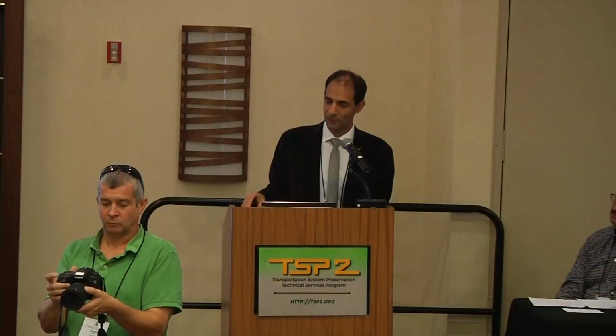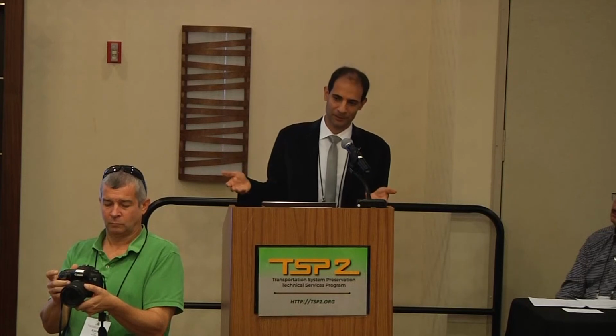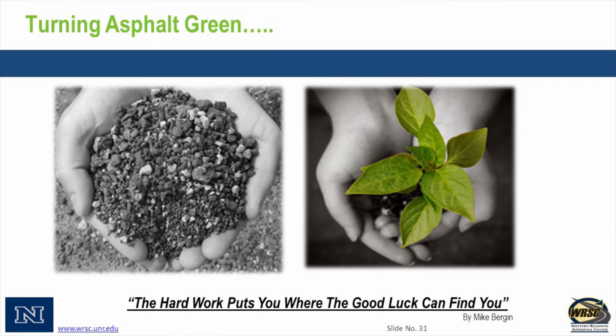Going back to your earlier talk, what was the optimum time for the second slurry seal? In terms of years, it's basically 4 to 6 years from the first one. In terms of PCI, which I like more, because most likely you can take this and implement it in your agency better, since the climate is different and the material is different. It might take you maybe 5 years for the first slurry seal to reach 90, whereas in Washoe County it may only take 3 years because the environment is different. Or if I take that data down to Vegas, which is a totally different harsh environment, maybe in 2 years I will reach 90 and need to do the treatment. So if you want to take something out of this, I would take more the PCI values and try to compare them: when do you reach those values on your roadways, rather than the number of years?